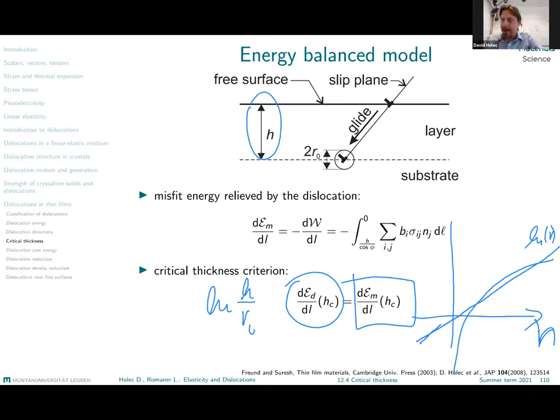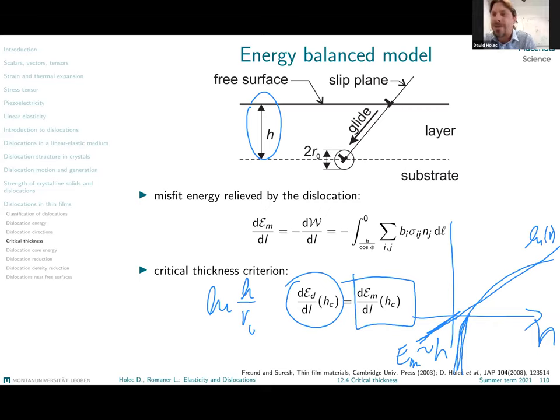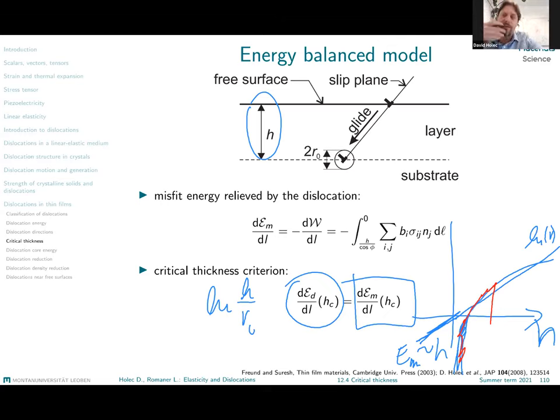So what does it mean? This line, which is not very linear, is the misfit energy going as a linear function of thickness. We say that the dislocation energy is negative for very small thicknesses of the film. Well, this is nonsense — we cannot have energy gain by introducing the dislocation. It simply means that anywhere in this area, we are in thicknesses where our elastic theory breaks. We are essentially inside the core radius, so the whole evaluation makes sense only from core radius onwards.